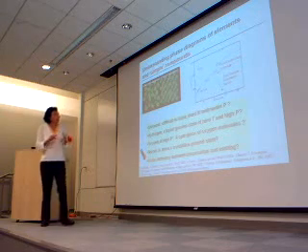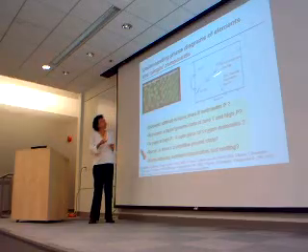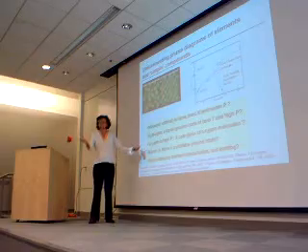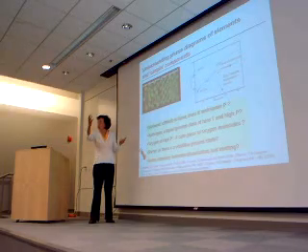And if you have a potential which is fitted even to the best quantum chemistry calculation ever, at low pressure, this potential will never give you dissociation events correctly. And so here it's particularly important to have ab initio molecular dynamics, where at each step you compute the forces on your atoms and let your system do whatever it wants to do. And so in water and in ice, pressure speeds up dissociation quite a bit under certain conditions.